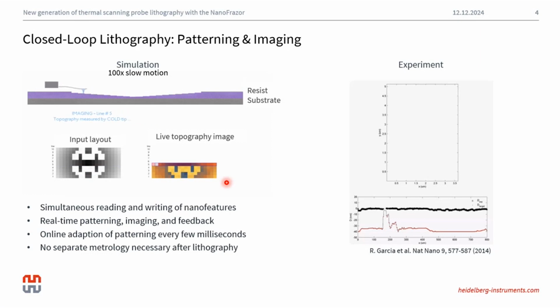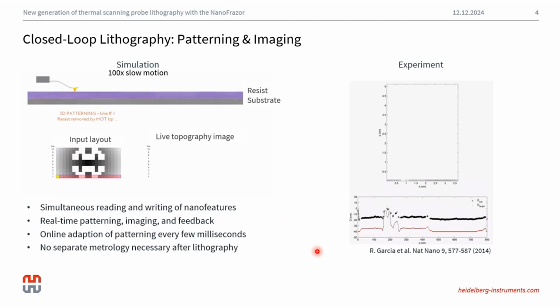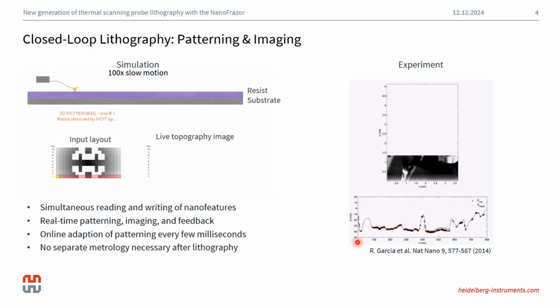So we have a live feedback to improve the patterning, which is running in the background. This is a simulated video of how this would look like and how the topography image would be built up in the NanoFrazor system. What's really powerful about this technique is that we don't require a separate metrology step after lithography to judge the quality of our written features. On the right-hand side, we see a video which was captured also using a NanoFrazor system by some of our collaborators. At the bottom this time, we see a cross-sectional profile of the target depth going line by line, also in this grayscale example, and also the measured depth and how they both follow each other quite well.